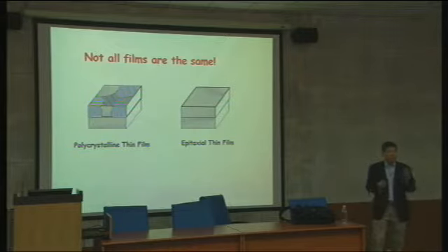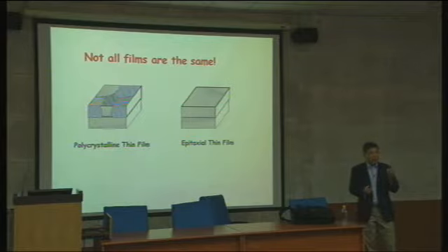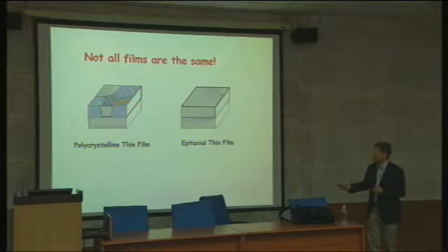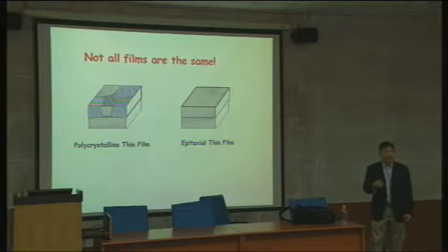The problem is that yttrium barium copper oxide superconductor has an extremely small superconducting coherence length, which means the wave functions overlap and superconductivity can be reached, but that is only 1 or 2 angstrom. It's a very, very small coherence length in the C direction. So if you have any disorder or a junk layer at the grain boundaries, a supercurrent cannot go through, and that's why it doesn't show superconductivity. Later, people figured out that epitaxial thin films have to be made. After they grew epitaxial thin films, they showed superconductivity.